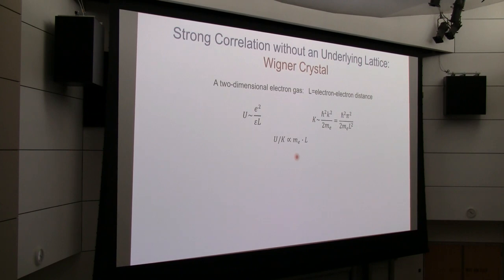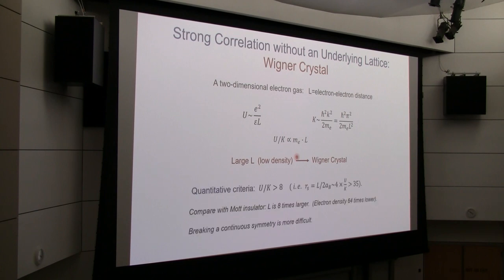The energy of Coulomb potential scales with 1 over L, and the kinetic energy scales with 1 over L squared. So when you have large enough L, Coulomb potential again will dominate and give you a strong correlation. And the electron will automatically form a crystal, known as a Wigner crystal. However, if you compare the Mott criteria and the Wigner crystal criteria together, you see there's a small quantitative difference. So in order to get a Wigner crystal, where you don't have an underlying lattice, you need the Coulomb potential to be roughly 8 times larger than the kinetic energy if you define it this way.